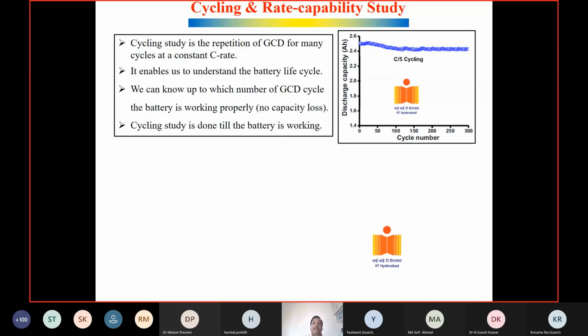So we do the charge discharge cycling. For C by 5 rate, that means per day you can do about 2 cycles. That means 300 cycles will take around 130 to 140 days to complete at C by 5 rate. Okay, so at 1 C rate per day you can get 12 cycles. That means per month you can do something like 360 cycles.